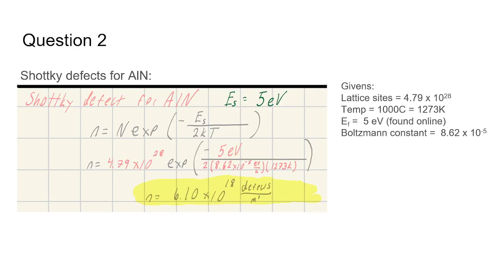For the Schottky defects of aluminum nitride, it's the same procedure as before, except with another activation energy of 5 eV. So again, we input our lattice sites, which is 4.79 times 10 to the 28, exponential negative 5 eV divided by 2 Boltzmann constant and temperature. And that gives us 6.10 times 10 to the 18 defects per meters cubed.